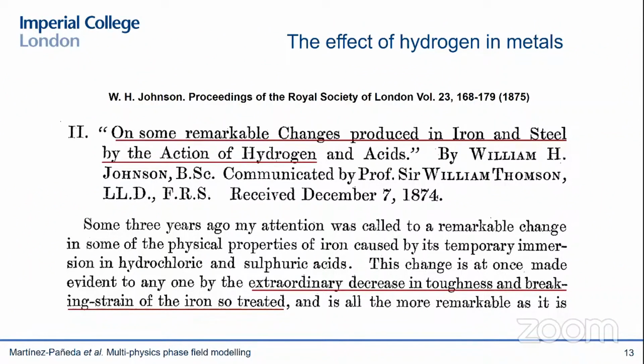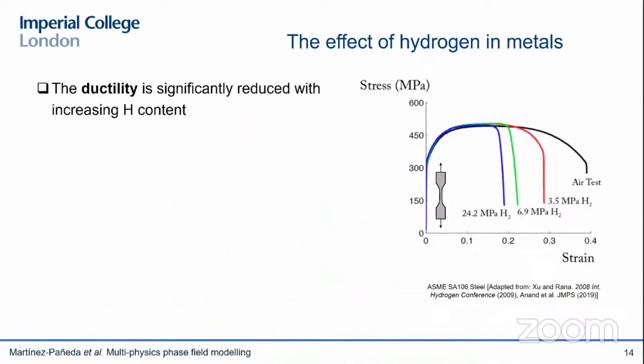And in those days, it was very rare to see words such as remarkable or extraordinary in scientific papers. But the way hydrogen interacts with metals is indeed remarkable and extraordinary. So one of the things that we observed is a very significant reduction in ductility with increasing hydrogen content. You can see this here. These are uniaxial stress strain curves. And you can see that if I introduce hydrogen into my samples, I get a very significant reduction in the